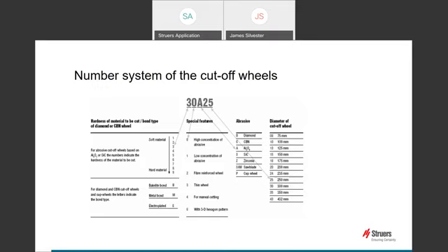If we take the Discotom 100 as an example, softer non-ferrous materials would require cutoff wheels with an S for silicon carbide abrasive, and the size could be either 25 or 30. Ferrous materials would need the aluminum oxide abrasive wheels, and they would be identified with an A abrasive. Again, as it's using the same machine, the 25 or the 30 would fit this variant of Discotom.